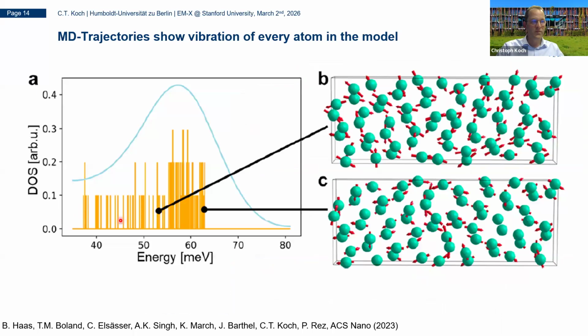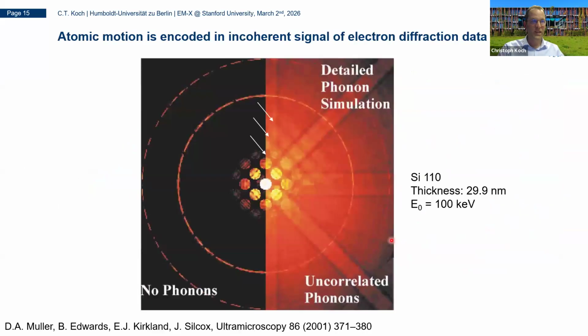You can see there are different eigenmodes which have, of course, different spectral density. This is around the 60 milli-eV peak. Quite a few of them focus in this range here. And you can see now these atomic displacements associated with each of these energies. So we have the atomic displacements in the model, which reproduce the EELS experiment. And now we have something realistic in hand that we can do some simulations with and see if we can also recover the vibrational eigenmodes, not just the energies, but also the correlations between the motion of the atoms.